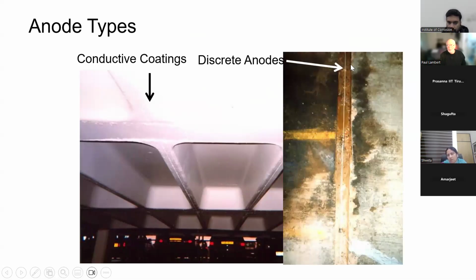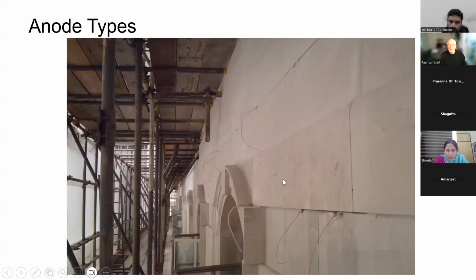And in this case, on the ribs, which have got more steel in them, from the top of the deck, we've got one, two, three discrete anodes, rod anodes drilled in and linked by titanium wires, and the whole thing made good. So that's using a different type. You can combine these as necessary to get the effect you want.